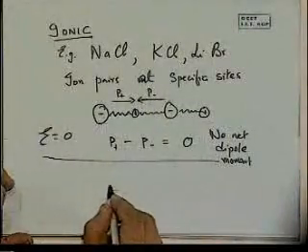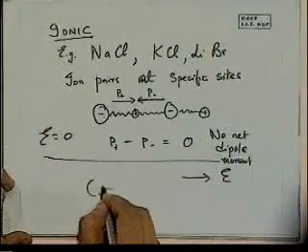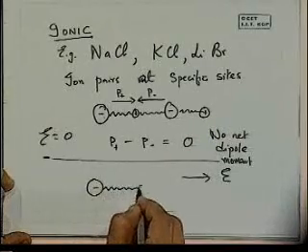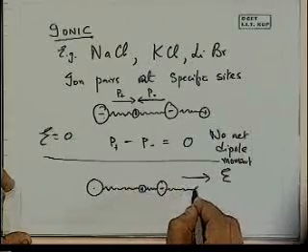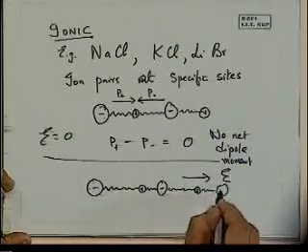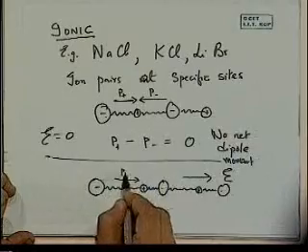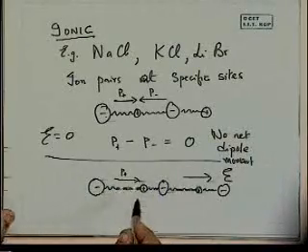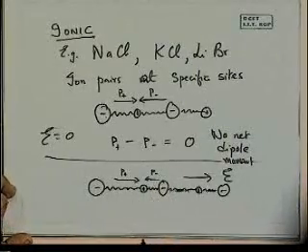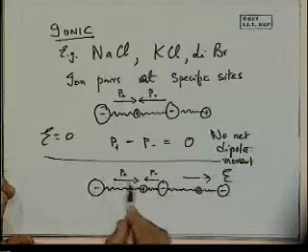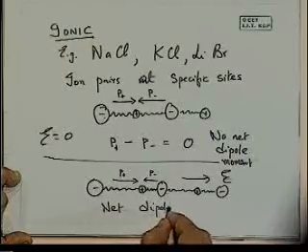So we will get something like this, the negative ones moving in this direction and the positive this way if we have applied a field, namely something like this, because they've moved, shifted. As a result, now this is my one dipole moment, spacing is this much, and the other one, the dipole moment is this. So instead of now being alternately equal and opposite, I'm ending up with a net dipole moment in the presence of an electric field.